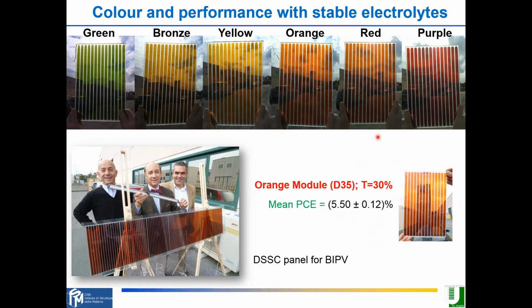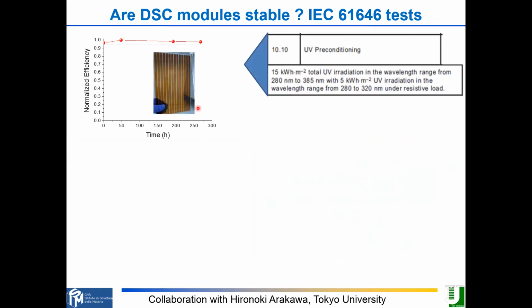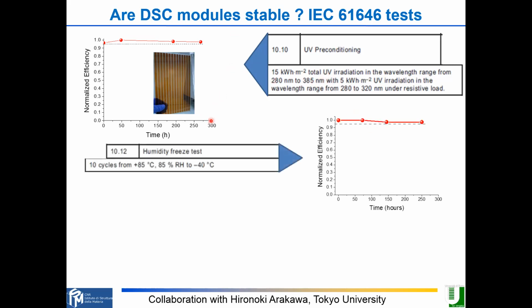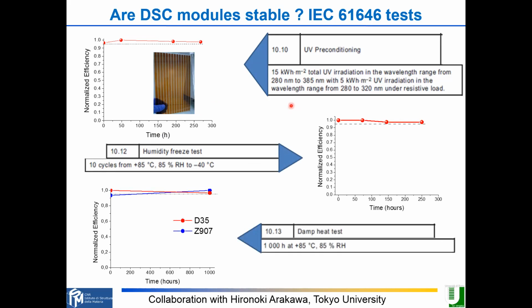The main effort we made was to stabilize the technology, because at the very end you need to bring this to the market. I believe it was a 5-year effort to stabilize the technology. And then you see the main IEC 61646 tests, like UV preconditioning, humidity freeze test, and damp heat test. All of these can be passed with a variation of efficiency of less than 5%, so a relative variation. So you can see that this kind of technology is quite rugged. And we had a nice collaboration with Japan, with Professor Hironoki Arakawa from Tokyo University.